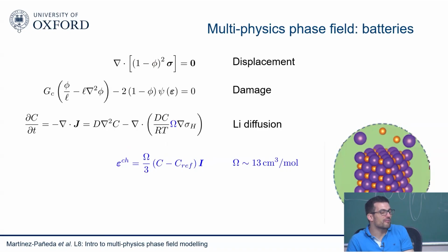I mean, some people have used phase field to model the lithiation process. So I guess they will see a little bit of change in stiffness. We didn't see that much. However, there were two effects that people reported in the literature that they suspected would play a big role, so we incorporated them into our model. One was the diffusivity will be dependent on concentration, and this apparently mattered quite a lot. But also this partial molar volume, which will govern these chemical strains, will be dependent on concentration. And they can measure this with some GITT experiments and so on. And there we saw a bigger effect. But although there's a community doing phase field to model the lithiation process, we never thought there would be much of an effect on the stiffness. So at least we haven't done it yet.